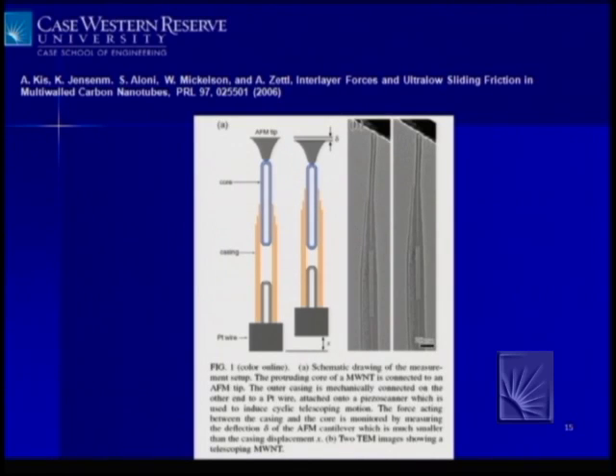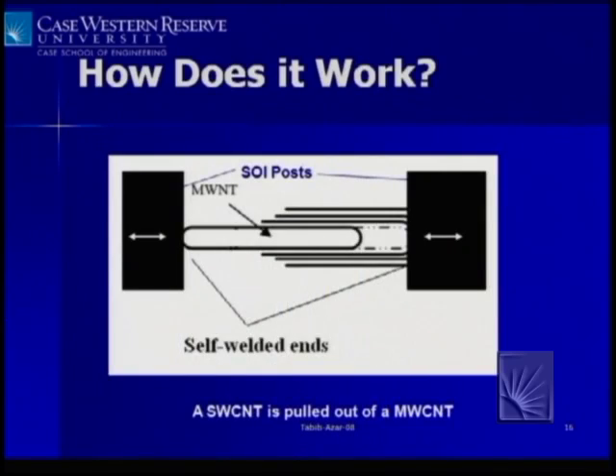This careful study was done by my friend Alex Zettl at Berkeley, who put these multi-walled carbon nanotubes in a TEM and attached 2 posts. In this particular case, one was an AFM tip. By the way, we have a couple of these in my lab on the 7th floor in Glennan. If you guys are interested, you're welcome to contact Lucian, who is sitting in here, and we'll give you some demos regarding how they work. And this is a TEM image, so you can see he pulled it, and then they became elongated, and as they telescope out, the resistance changes.